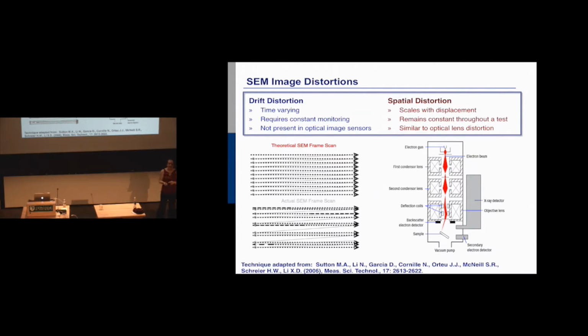When you're in an SEM, a scanning electron microscope, the issue is that A, you're not collecting every point at the same time, and B, you still have lens distortions, except they're different. Every lens has a distortion in it, whether it's bending light or bending electrons, it's still going to have a defect. There's no perfect lens. The problem is that an optical lens has pretty much a parametric distortion. When you have an electron lens that's bending electrons, it's going to depend on a bunch of factors like the alignment of the system that you have to account for every time you do the experiments. And it's not going to be this pretty parametric. It's going to be something different every time.